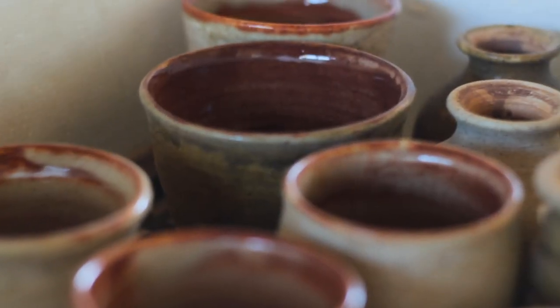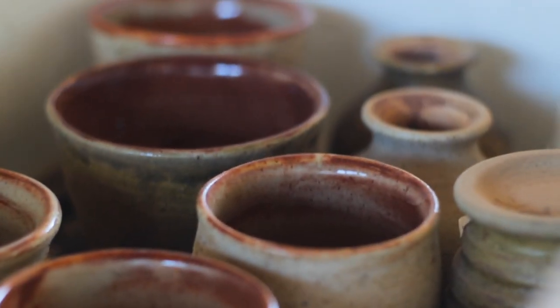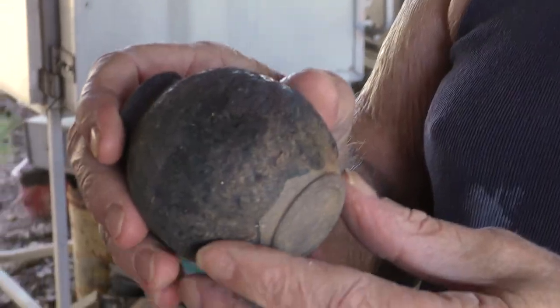At the moment we'll be talking about ash glazes. You can do a basic glaze on pottery by starting off with ash from whatever you've burnt in the kiln and the clay. Start off with a 50-50 mix, and then if it looks as though it might be interesting, you could refine it a bit or add other glazes to it.